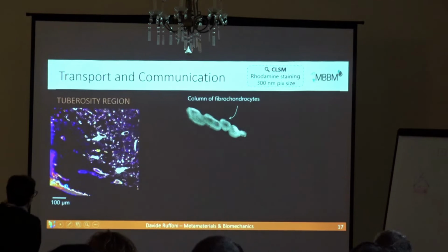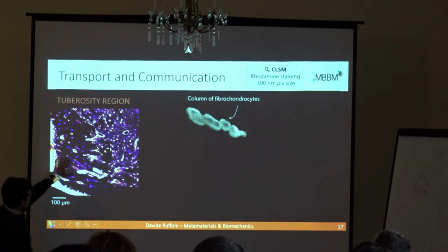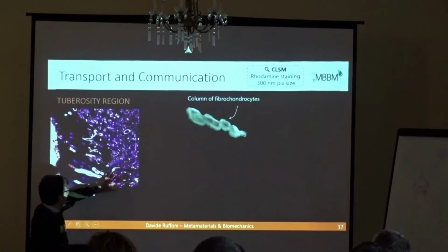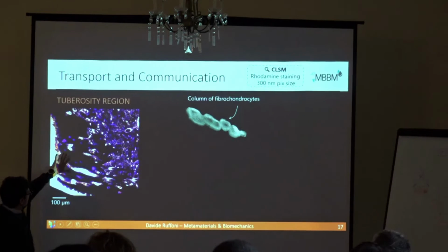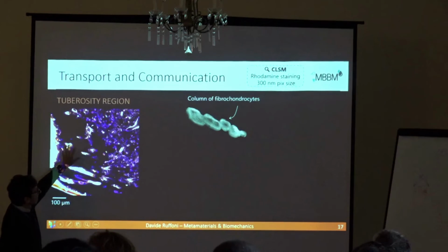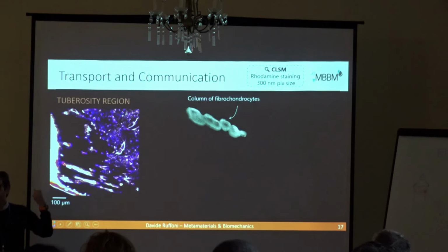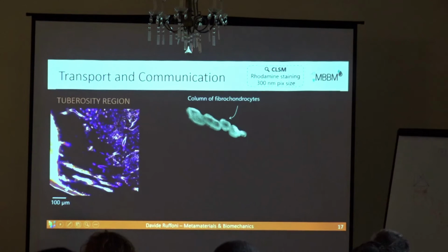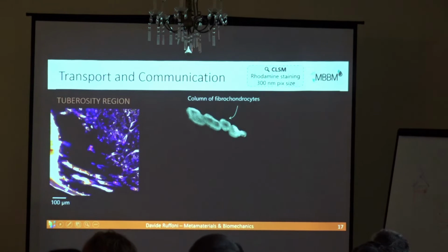So we are scanning through the cross section. This is fibrocartilage and this is bone. What you see is that there are some regions in fibrocartilage that get colored. This means that our staining agent could diffuse from bone to fibrocartilage. And the only way to diffuse is through some pores, because those are highly mineralized tissues, so there is no diffusion inside the tissue itself. The staining can only travel through the pores.